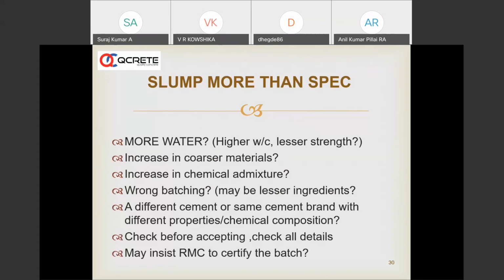If the slump is more, what do you do as one of the important steps in terms of retrospective control? Let us say we take the concrete and we find that the slump is more. Why does this happen? The slump can be because of more water. It could have come because of a wrong moisture content given in the batching plant. That means it will lead to a higher water cement ratio. Maybe the aggregates, which during the mix design were taken with a certain gradation, have become coarser. Sand has become coarser.